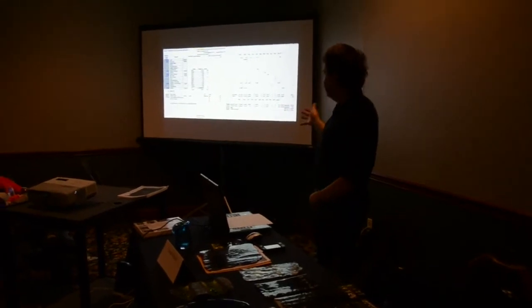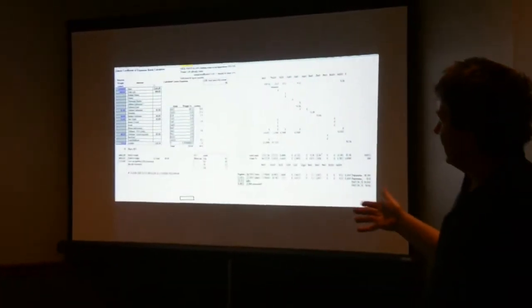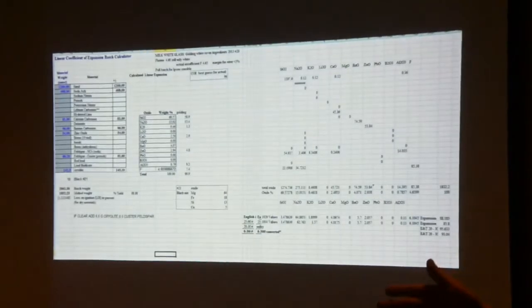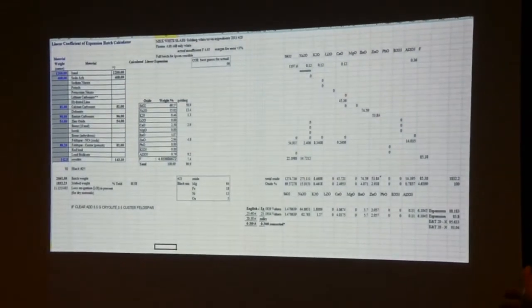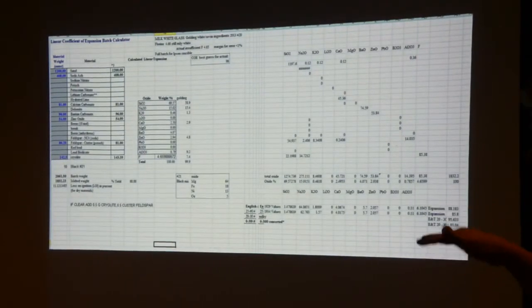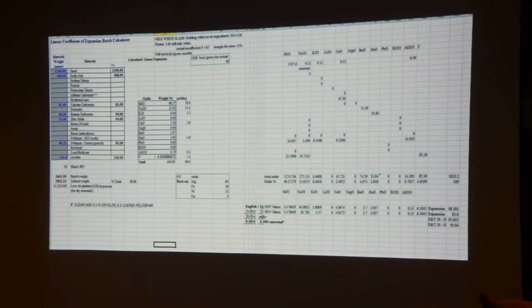What we got here is all the ingredients. You've got sand on the top far left, and then soda ash. You can add some potash, some calcium carbonate, which is whiting, which is another primary flux. And you can control the coefficient of expansion depending on which ingredients you add. System 96 is very popular. 90 is another one, and you can actually take one in a big molten batch and add a little extra of this and that to change it over to the other one.